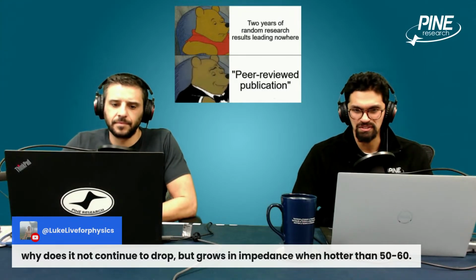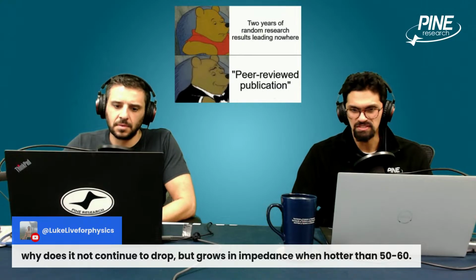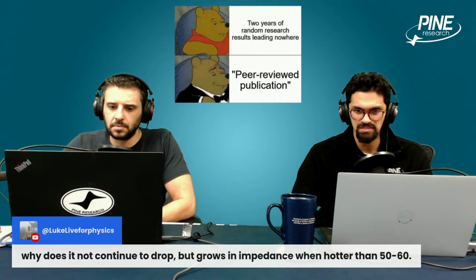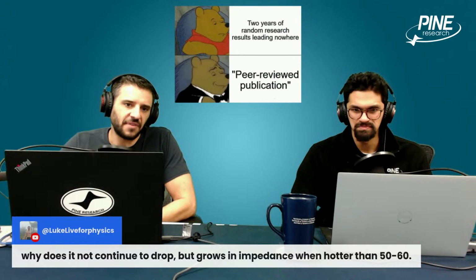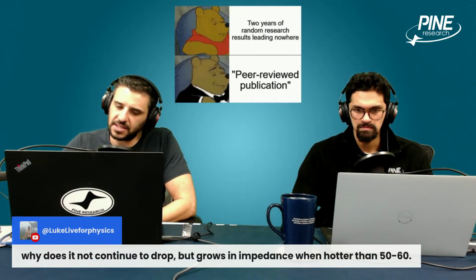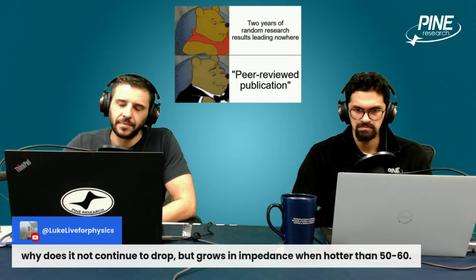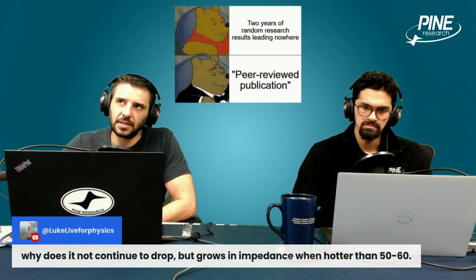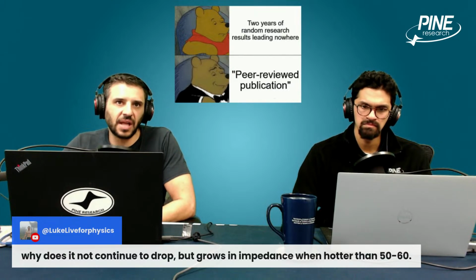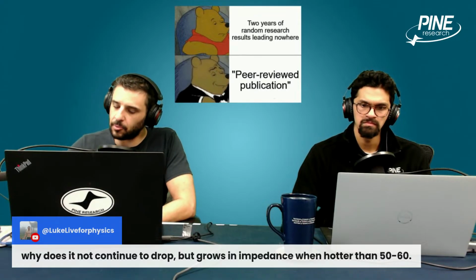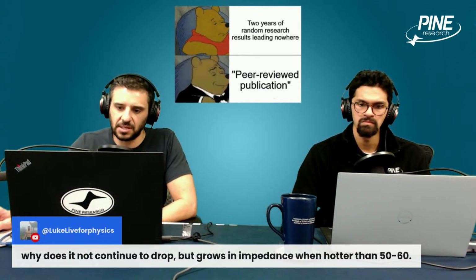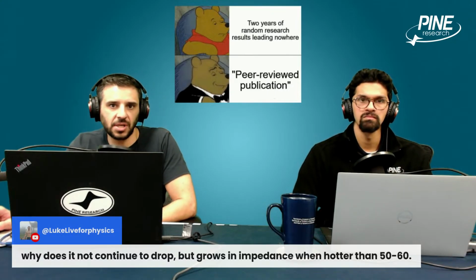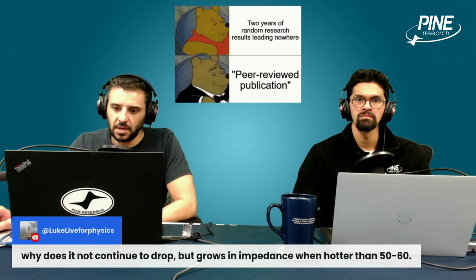I don't know what they are for 18650s and 2170 cells, but you've got graphite in the anode, and you probably have NMC or NCA, maybe cobalt oxide, could be iron phosphate. It just seems like probably there's some undesirable process that's occurring once you start increasing the temperature. Again, it could be SEI degradation, decomposition, modification could be happening.